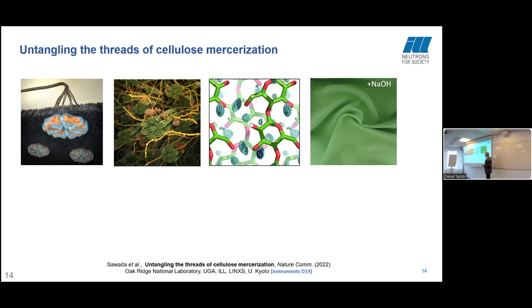And we also looked at the crystal structure of cellulose and mercerized cellulose. For some time it's been known that rather than the chains all having the same parallel direction, every second chain has actually changed direction. And so the crystal structure is anti-parallel. And that always perplexed me. How can you have a nanorod that's thousands of monomers long, treated with a little bit of sodium hydroxide, and then get a crystal structure where the chains are now anti-parallel? I just find that really interesting. How can that happen?